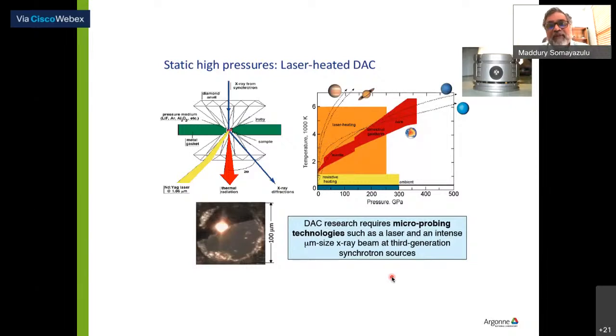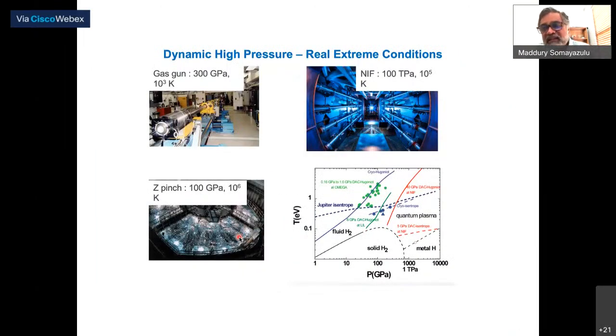I will come into what I mean by terapascal and 100 GPa shortly. But essentially, what you do is you take a material which you want to study and squeeze it between two diamond anvils and probe it with a laser beam to be able to achieve the pressure temperature conditions. And of course, as all of us know from our high school, pressure goes as force per unit area. So the higher the pressure you want to go, the smaller is the area. Smaller area implies that you need smaller microprobing technology, and that is where synchrotron beams come into play. Okay, but that's in static pressures.